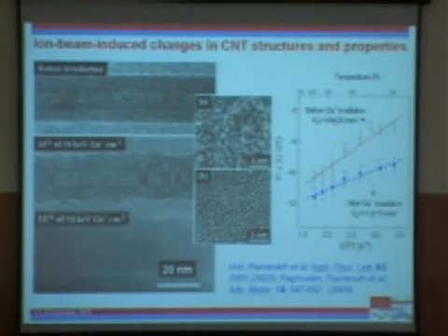Okay, what does it do to the electrical properties when I just hit nanotubes with ions? You can see that here this is actually a transmission electron micrograph showing the basal planes of graphite, or of the graphene sheets that are folded into the nanotubes. When I bombard them with ions, you can see that there is defect creation and reconstruction. The shapes are changing. This is the atomic scale structure. And in this particular case, when we have very high doses, it is not a tube anymore. You can see the hollow in all these cases, but in this case, there's no hollow. And so it actually becomes a nanorod.